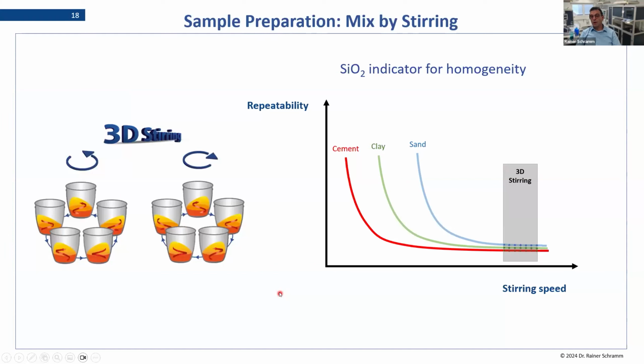Okay, let's talk about homogenization. And there are different systems in the market. Either you use, like our system, a circling homogenization, or some other systems use the rocking. So you just go back and forth. If you want to be sure that your agitation is working, you could always have a look into the silicon oxide. And this is my experience, that this element is one of the most critical elements concerning your agitation. So you could always use the result of silicon oxide to verify if your agitation is good enough or not.